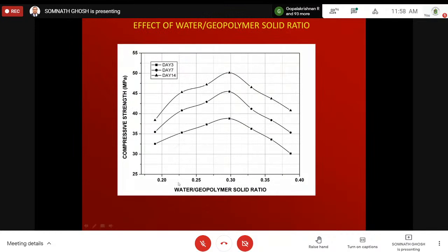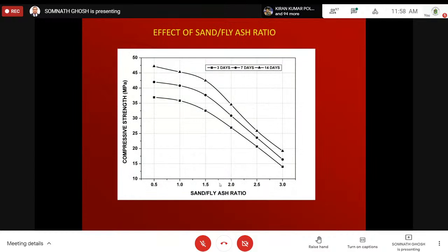This is the water geopolymer solid ratio, where solid means fly ash. Or if you use fly ash and slag both together, then at a particular water to source material ratio, you are getting very good result. But beyond that, it is decreasing. You have to be very careful about the water solid ratio. This is the sand and fly ash ratio in the composite. If it is reduced, then you are getting higher strength. Obviously.